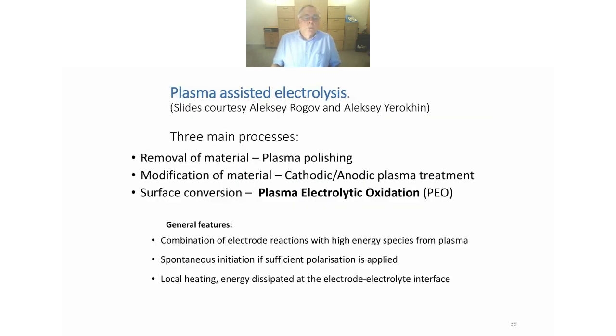At Manchester, we've done quite a lot of work on the plasma-assisted electrolysis process, and these slides are from Alexei Rogov and Alexei Yorokin. Alexei leads this group, and for plasma-assisted electrolysis, we can remove material, for example, by plasma polishing. We can modify material through, for example, cathodic and anodic plasma treatments, and we can convert surfaces, for example, through plasma electrolytic oxidation. So basically, you combine electrode reactions with high energy species from the plasma. You can spontaneously initiate the process if you apply sufficient voltage, and you can get local heating, and the energy dissipated at the electrolyte interface allows you to convert the surface of that electrode.